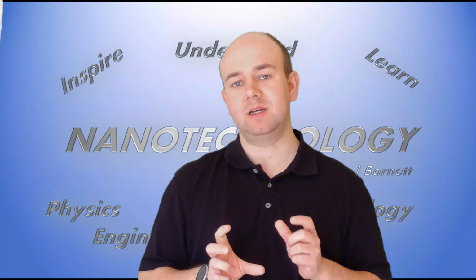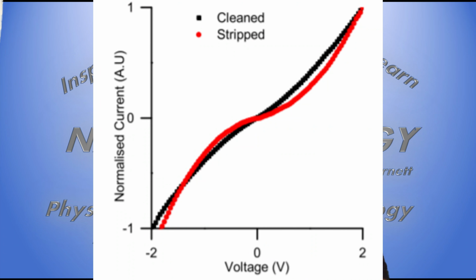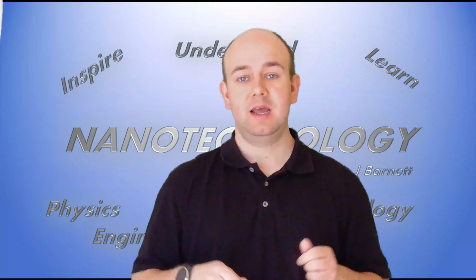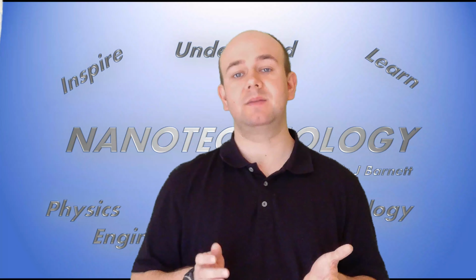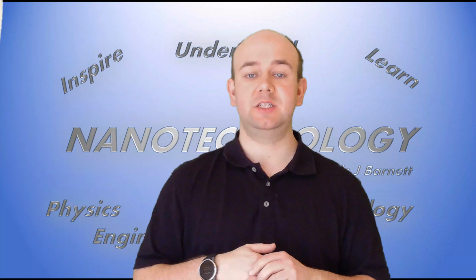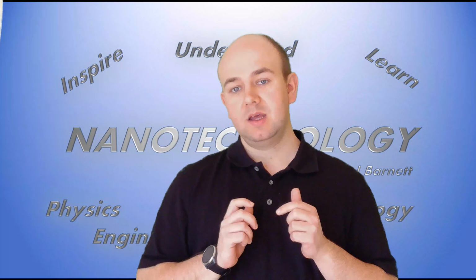What we also saw in this paper and the previous paper is that the IV curves moved from an almost linear shape to being more rectifying, and this again is because we're removing the defects, which add more electrons to the outside of the nanosheets, and when it comes into contact with a metal you get some upwards band bending, which causes the more rectifying nature of the IV curve.